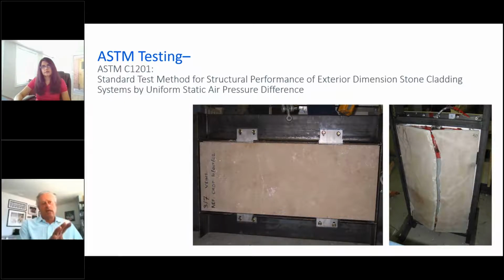And what we try and do is get some panels that show the different veining in them, and we can load them up and see what the effect of the vein has on the assembly when it's loaded uniformly on the panel. So you can see two examples here. The one on the left is a long horizontal with connections top and bottom that would get loaded up to failure. And in this case, the failure actually occurred at the connection locations. And on the right-hand side, you can see another assembly where the actual panel failed. It failed in the middle, but the anchors were still holding the panel in place.